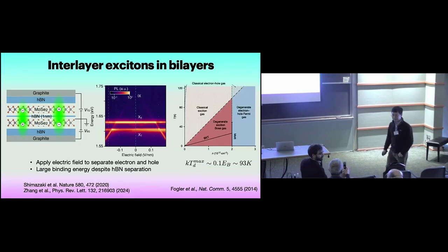Yeah. How did you measure the binding energy? Yeah, so that's an excellent question. Here I can measure the exciton energy at 0 field by extrapolating to 0 field. So this tells me the interlayer exciton energy. And I can also measure the band gap from the Rydberg states of the 1s exciton, which I didn't show. And from there, I can get the band gap minus the exciton energy. So I measure the binding energy directly.